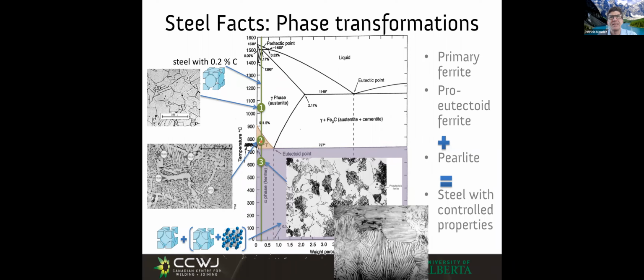Now it's red hot, right? It's quite red orangey, so we're looking at something that is glowing red. In this case, we have a mixture of austenite and ferrite. So you see these austenite grain sizes, the austenite grain boundaries we have here. The ferrite starts to grow on the austenite grain boundaries.